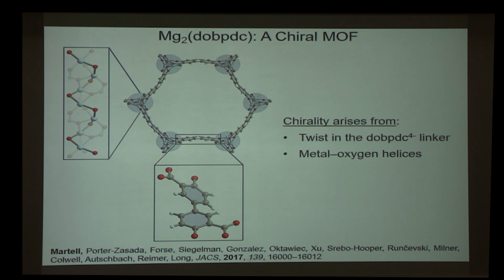The MOF that I was working with during the CO2 capture project, I realized was actually a chiral MOF. This material, magnesium DOB-PDC, is chiral because the organic linker is permanently locked into a twisted conformation that is chiral.